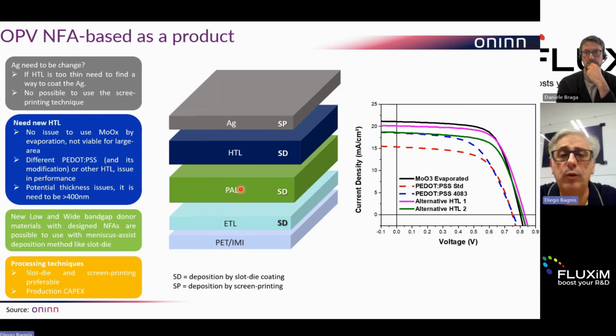On the other side, using the new donor material with the non-fullerene acceptor, you also improve the absorption coefficient of the photoactive layer. And so the thickness of the photoactive layer is much thinner than the standard one, which is normally around 300 nanometers. With the non-fullerene acceptor, this is around 100, 120. That is really, really thin.